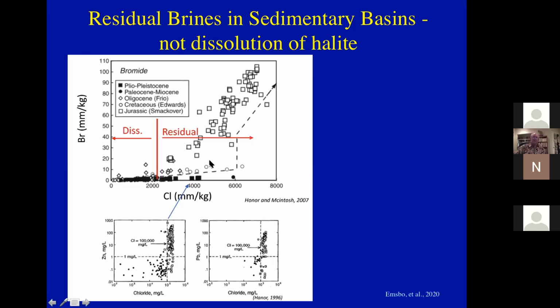On this upper diagram here, the vertical red line separates essentially the field of brines that were generated by dissolving salt, and brines that were generated by the evaporation of seawater. And you can see in these two here, which is zinc and lead concentrations in some of the Gulf Coast brines, that the metal concentration increases as the brines get more chlorine rich.